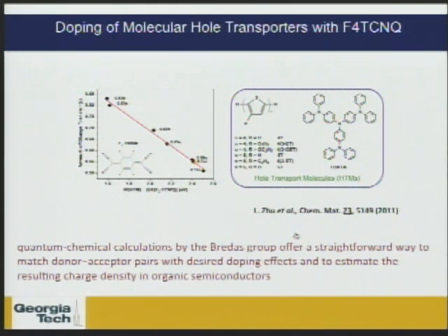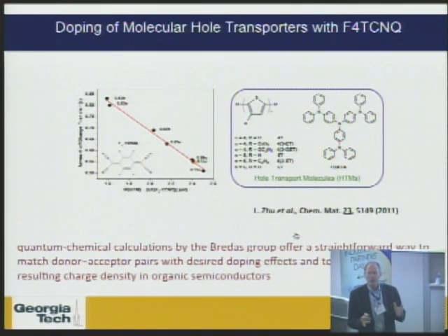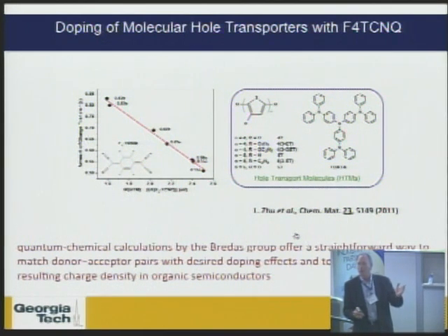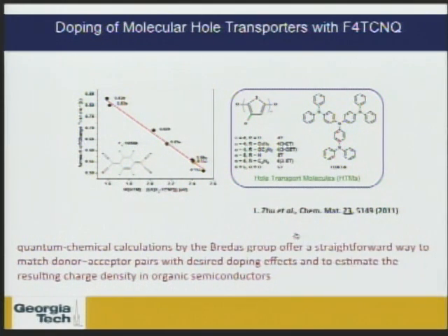Now, as we think about carrying out these types of oxidations or reductions, in essence doping reactions, one thing to think about when you think about polymers is that we have a continuum of doping states. If we think about a salt, we might have a positive ion and a negative ion. But as we look at interactions, for example, in this F4TCNQ, as a function of various materials, you can see that there's a certain level of charge transfer as a function of how the dopant interacts with the polymer. And so there's a matching between the dopant and the organic system, both polymeric and in this case a molecular hole transporting material that controls the level of that charge transfer.